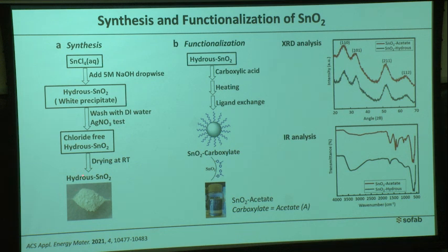That's why it's hydrous tin oxide. I tried to make a stable dispersion of this tin oxide in a perovskite-compatible solvent using hydrous tin oxide, but I was never able to - that never worked. After that, I selected a second route: to bind tin oxide by attaching some ligand, some extra group, onto the tin oxide.